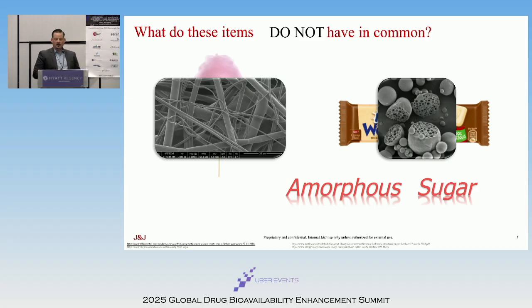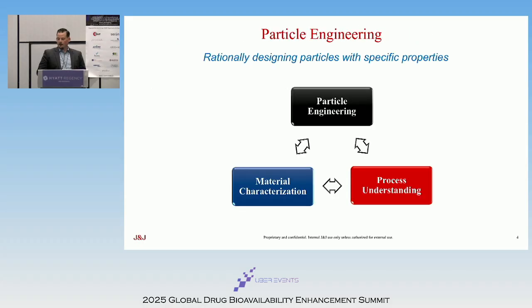So the cotton candy is actually composed of long filaments of sugar created by heating up and then rapidly cooling down the sugar, essentially to stop it from recrystallizing. Whereas the Milky Bar, which you could, before I covered it up, see on the label, touted 30% less sugar. It's using these really complicated microparticles, where we can see in this SEM image that it has a really complex internal pore structure. So essentially this even further speeds up the dissolution, which allows us to even further enhance the sweet effect using less sugar, hence the 30% less. So that was a result of creative particle engineering.